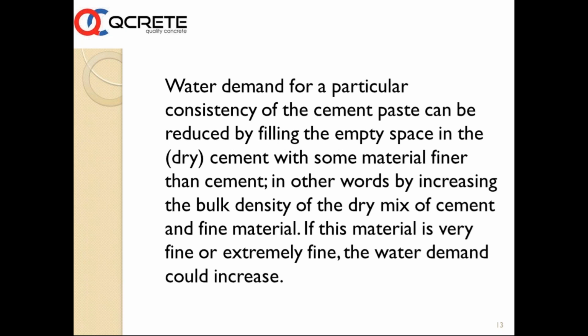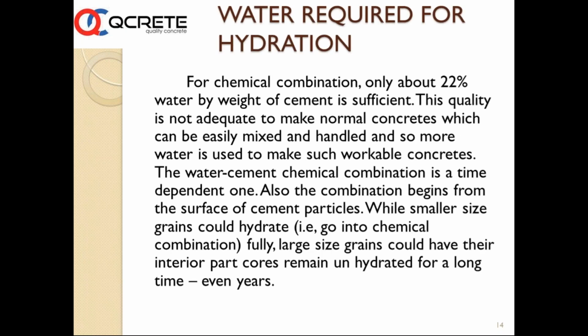In fact, one of the products in the market, which has about 12,000 square centimeters per gram of surface area, when we use it in concrete, there is a reduction of liters of water in the concrete. So up to about 15 to 20% one can use this fine material with a particular particle size distribution, taking advantage of the particle filling. If this material is extremely fine, the water demand could increase. Suppose the surface area is 70,000, then the surface area is very high, so the water demand goes up.